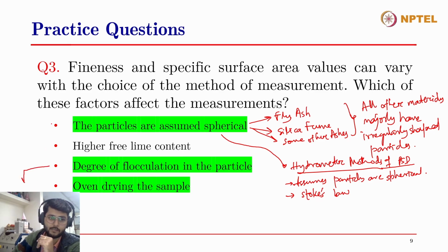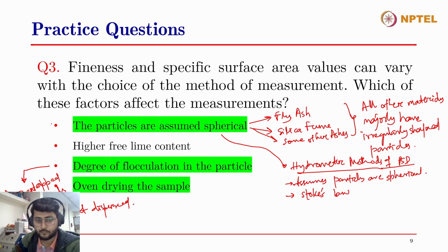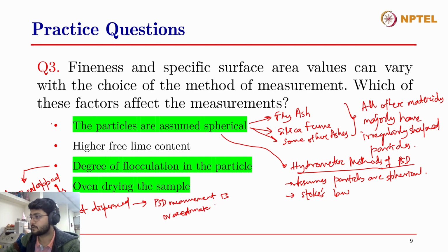When the particles are in a flocculated state, air is entrapped in these particle flocks. If the particles are not dispersed properly, if these flocks are not broken, then the particle size distribution measurement will be affected. It will overestimate the particle size, meaning that the distribution will be more on the higher side of sizes, even though your particles are actually smaller. It will be measuring the whole flock as a single particle, while the particles within that flock are much smaller in size.